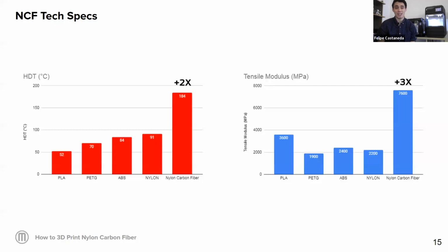Talking about heat deflection, right? If you compare it with all of our other standard polymers, PLA, PETG, ABS, even nylon, you're getting almost twice as much resistance to heat deflection as you would with any of the rest of the materials. So, you're going almost to 200 degrees Celsius. That's rather hot if you consider that 100 degrees Celsius is about the boiling temperature of water. Any one of these parts will take you all the way to 184, just about. So close to twice, or a little bit over twice as much as the next best material, which essentially is nylon. That's one of the reasons why we chose nylon as a base polymer.